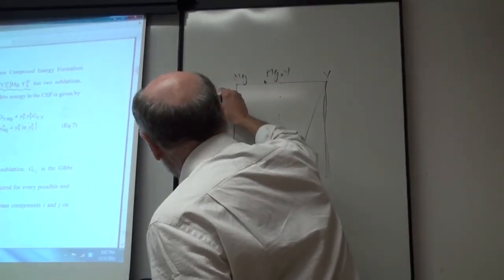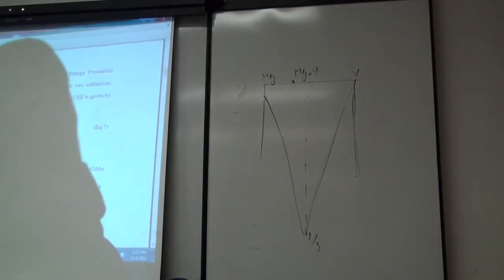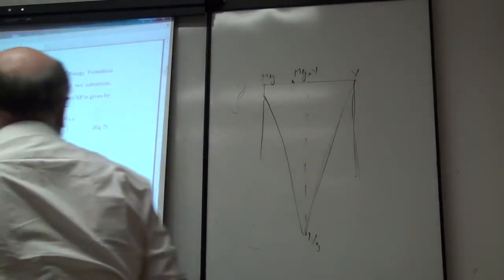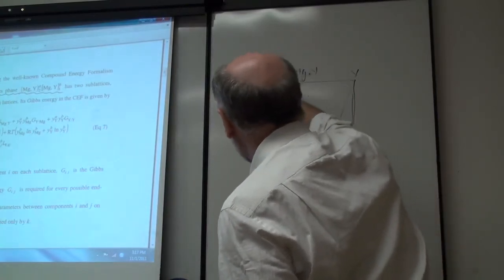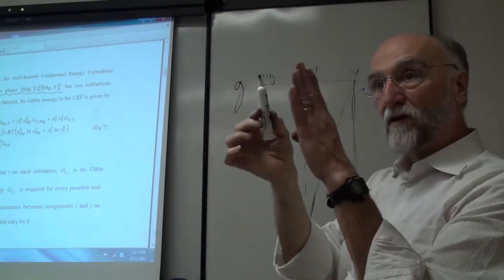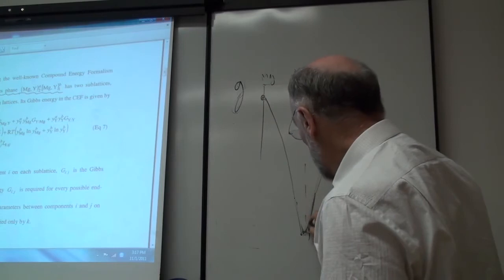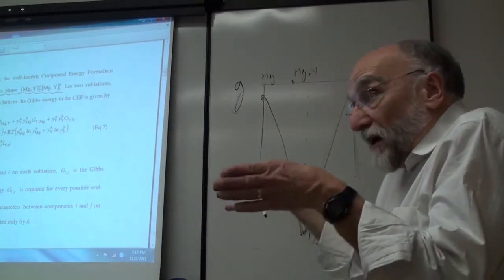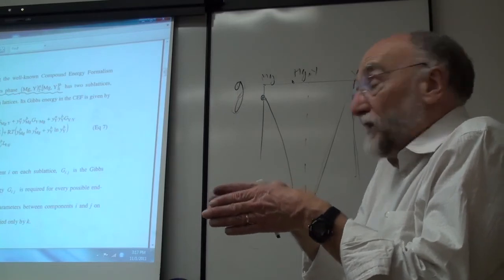Okay, so this point here is your G. This point up here, your compound, this is the area we're dealing with. On the phase diagram, remember, it was only over a very narrow region. This is the only region here that has any real physical significance. The sharper that is, the narrower the single phase region is.